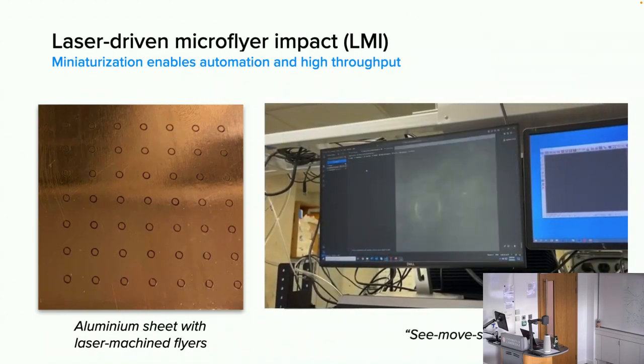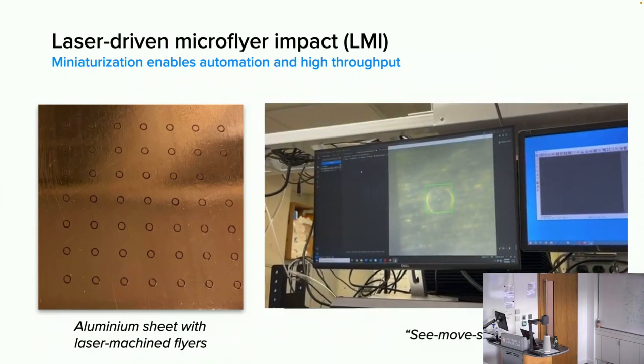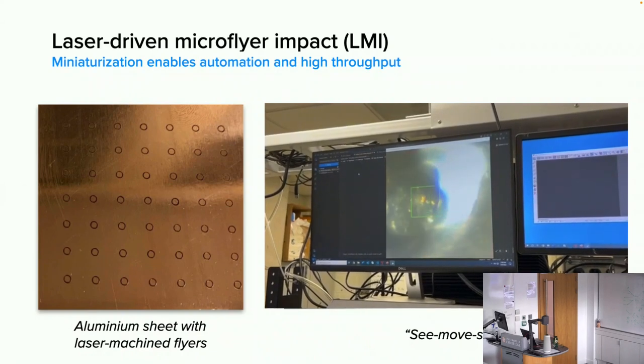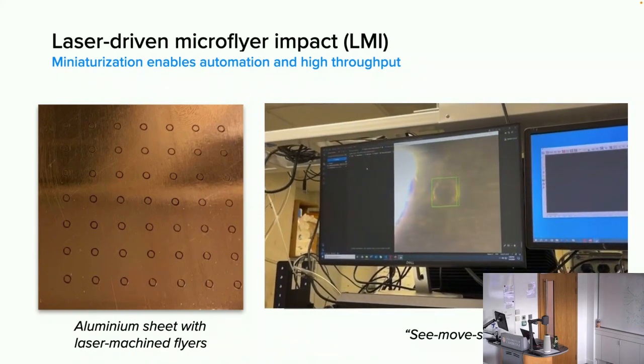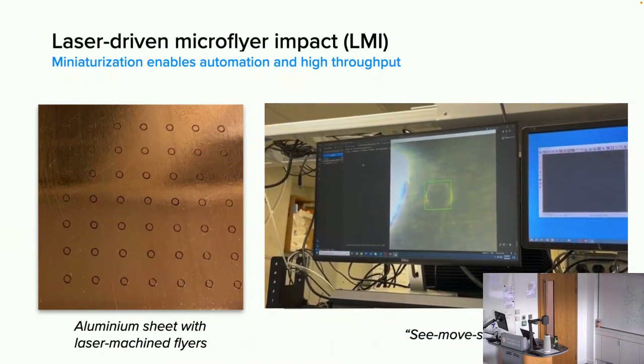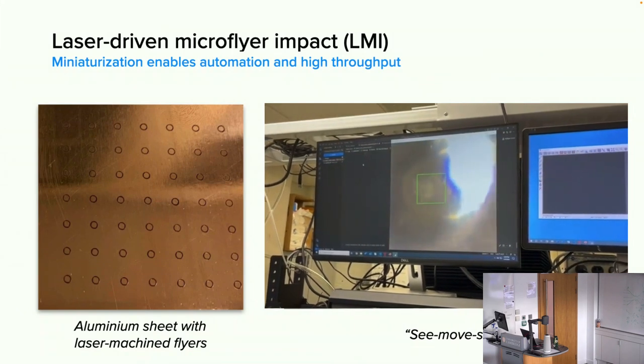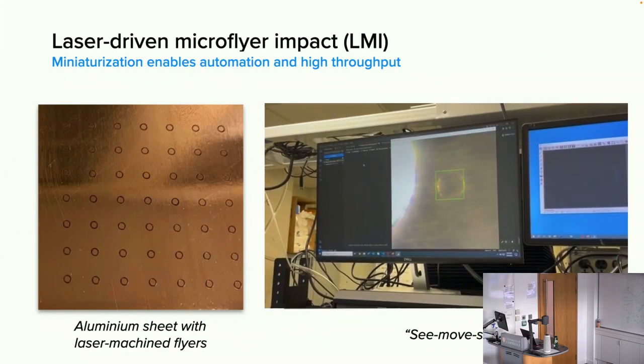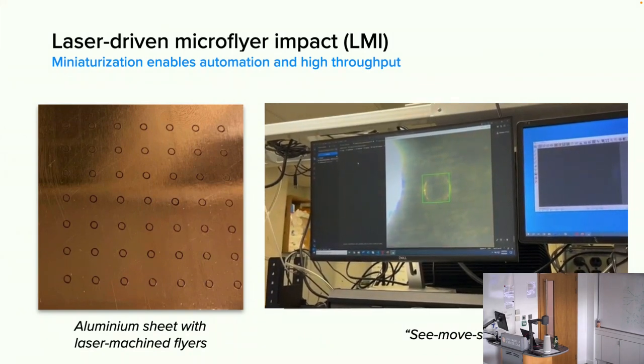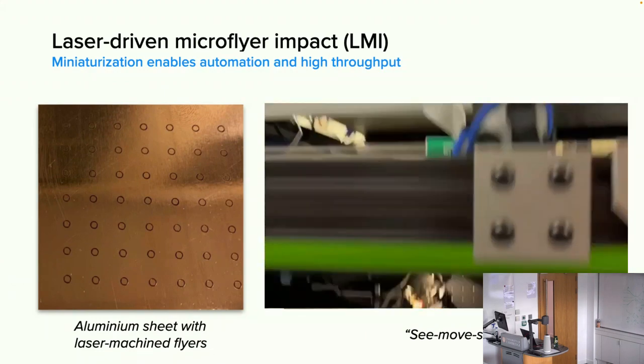And so some clever graduate students came up with a process that they call see, move, shoot, where they use just an off-the-shelf algorithm to locate where these circles are, to draw a box around them, to drive the stage, to put that stage and that dot directly below the laser. And now every flash you see here is another test.